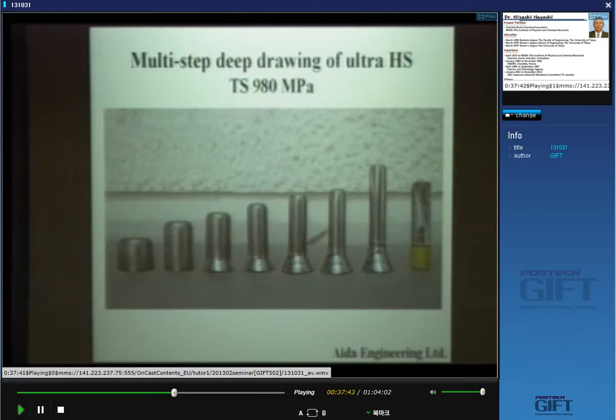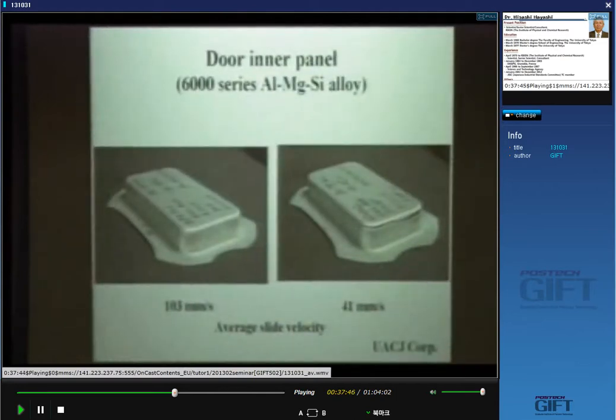And the other case, this is not real production, but we tried the improvement of aluminum alloys for the door outer panel of cars. Modified door inner panels, not door outer. And in this case, 6000 series alloys we used. And the left side is the forming limit. This is a slide motion. Slide motion speed is 103 millimeter per second. The right hand side is 41 millimeter per second.